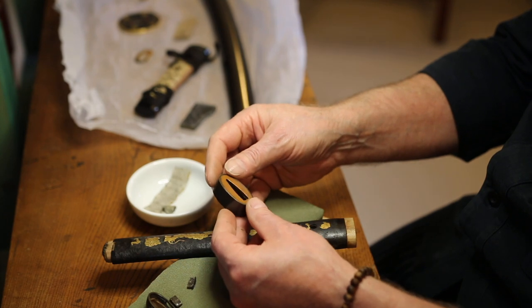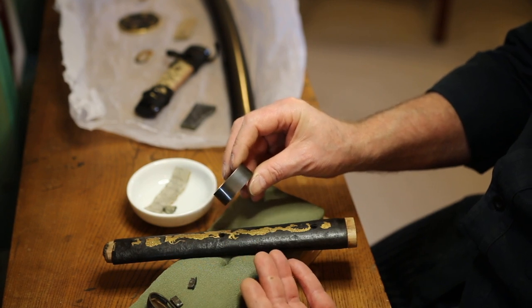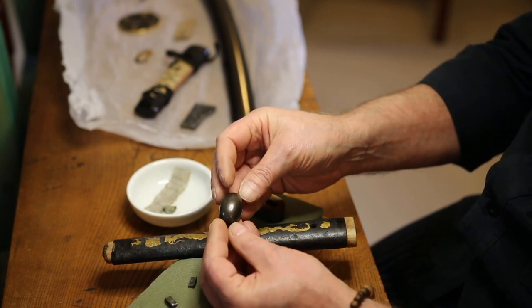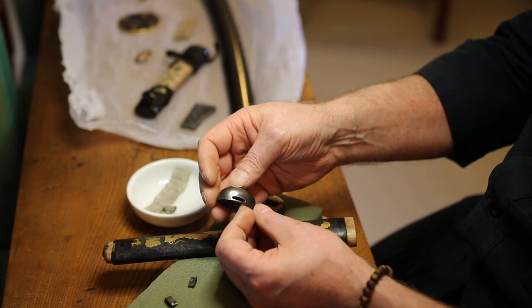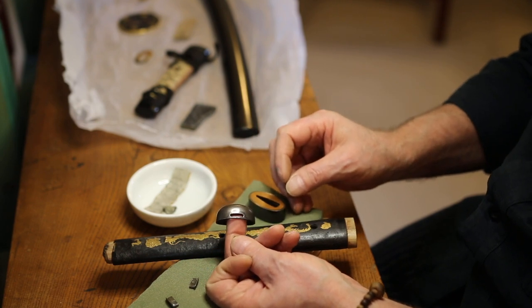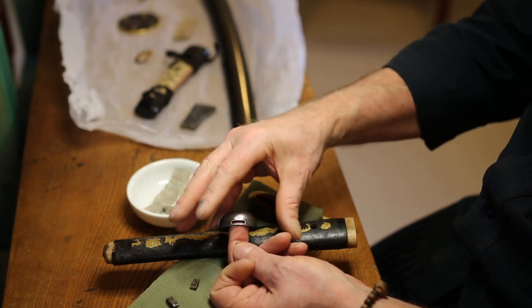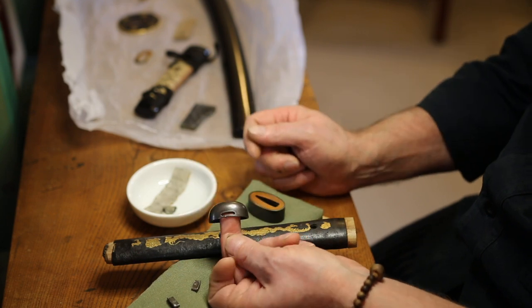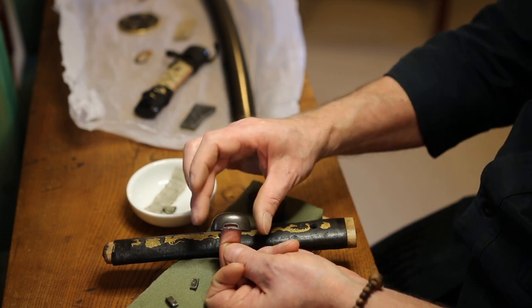The Shibuichi fittings — I really didn't want to lose the appearance as they are now. I didn't want to be getting into re-polishing and re-patinating. They're in relatively good condition. So I was able to, just with very careful cleaning, remove pretty much most of the surface grime. There's some really rather interesting grain visible. You can see distortion in the metal, in the grain structure, which reflects how the piece of metal from the flat was pushed into a die to shape it. We'll try and capture that in a better close-up in a minute.